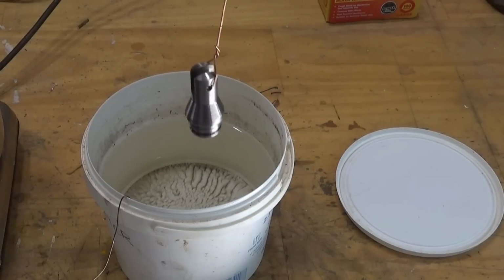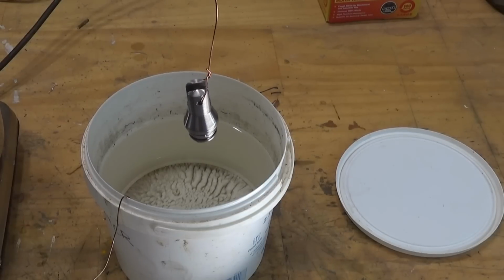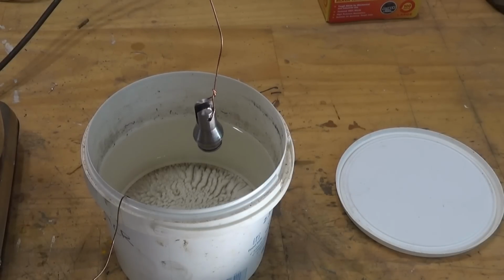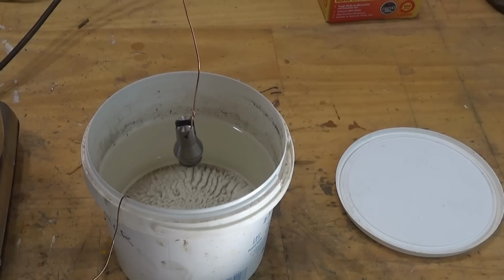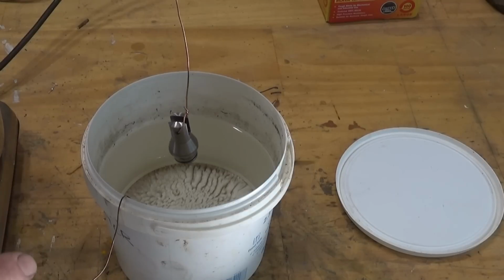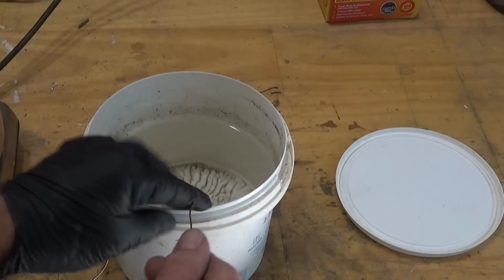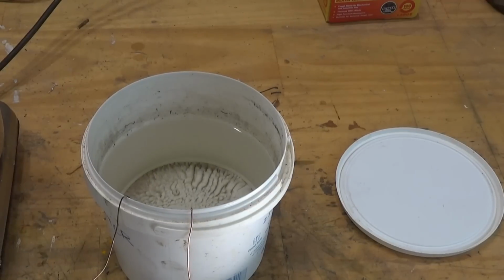Got all the parts wired on copper wire now, and they've been in a bucket of cold clean water, and now they go into this activator. It's called Metex M, but it's basically just an acid, and it activates the surface so that it will take the Parker phosphate coating more easily. So we'll leave them in for around about a minute to a minute and a half.